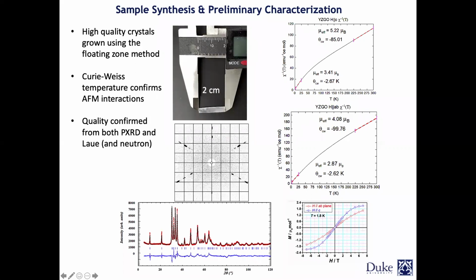And in these cases, we use a specific helium-3 setup. So we were able to go down to 250 millikelvin, 200 millikelvin. The next measurement that can be done is magnetization. We look at the collective magnetic moment in the sample. Because we have a single crystal, we can apply field along different directions and study the anisotropy of the compound. We can see which way is going to require more energy for the system to polarize its spins along that direction.